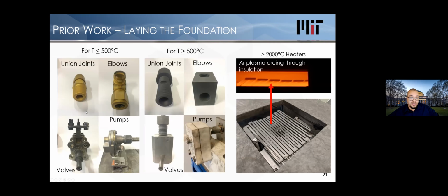This is just a glimpse of some of the components that we make. So for the components I showed, like you have a cyclone. When you get to the colder temperatures below about 500 degrees C, tin melts at about 232 degrees C. Below 500, you can actually use stainless steel parts that are coated in a ceramic, so you can get away with ceramic coatings. This is showing swage lock parts that we've coated, for example, with titanium nitride. Titanium nitride is like the gold coating you'll see on drill bits at Home Depot. This material is ceramic and it doesn't interact with liquid tin, so you can protect standard steel components with a commercialized coating that exists already.